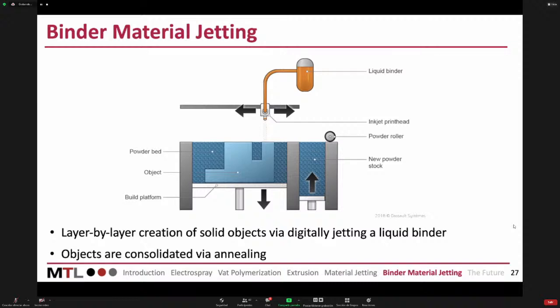So we have been using that technology because it is the technology that gives you the best resolution for metal printing of the commercial methods, and that has enough high throughput. So you can do with this technology way better than what you can do with, for example, lasers. And it doesn't have the issues with the thermal gradients and the stresses that you build up because you're melting, remelting, cooling so quickly. So it's a great technology.